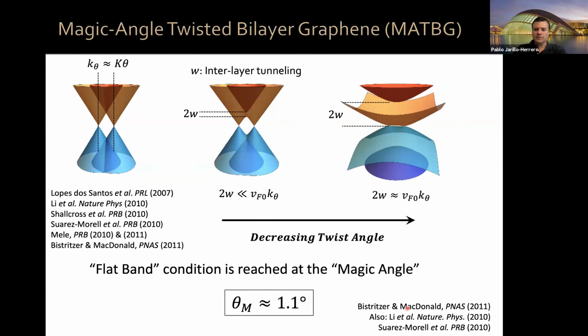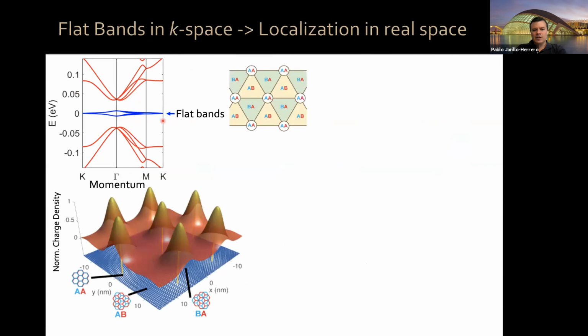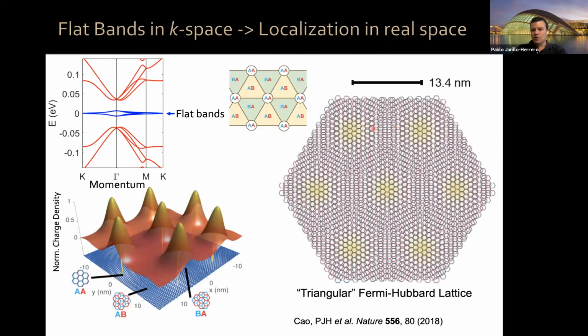And as I mentioned yesterday, there was very interesting single particle physics work, both theoretical and experimental, about a decade ago on the system. So then these flat bands, electrons in these flat bands, they like to localize, they like to be near regions of AA stacking. So this means that schematically, we have magic angle graphene. We have these regions of AA stacking where the electrons like to sit, and those are spaced about 13 nanometers apart, okay? And this is sort of the equivalent of cold atoms in a Hubbard lattice, except that because of the interesting topological properties that Andre already mentioned yesterday, it's a bit more exotic and there's no one-to-one mapping.